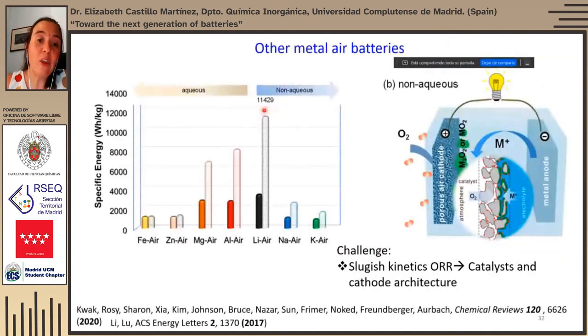If we were to compare the lithium air batteries with other metal air batteries, we see that in principle, the specific energy for a lithium air battery based only on the weight of lithium and oxygen is much higher than for any other chemical. But if we calculate the specific energy based on the weight of the decomposition products, this lithium peroxide or sodium peroxide, then differences are not that large. And especially if we take into account that aluminum, magnesium, although they are thermodynamically unstable in water, they can form some passivation layer that allows them to operate.